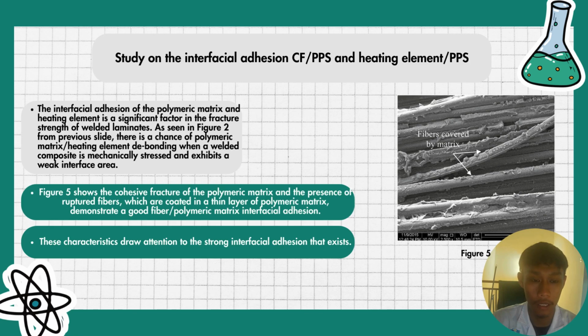Study on the interfacial adhesion of CF over PPS and heating element over PPS. The interfacial adhesion of the polymeric matrix and the heating element is a significant factor in the fracture strength of welded laminate. As seen in figure 2 from the previous slide, there is a chance of polymeric matrix and heating element debonding when a welded composite is mechanically stressed and exhibits a weak interface area. Figure 5 shows the cohesive fracture of the polymeric matrix and the presence of fractured fibers, which are caught in a thin layer of polymeric matrix. This demonstrates good fiber polymeric interfacial adhesion. This characteristic draws attention to the strong interfacial adhesion that exists.